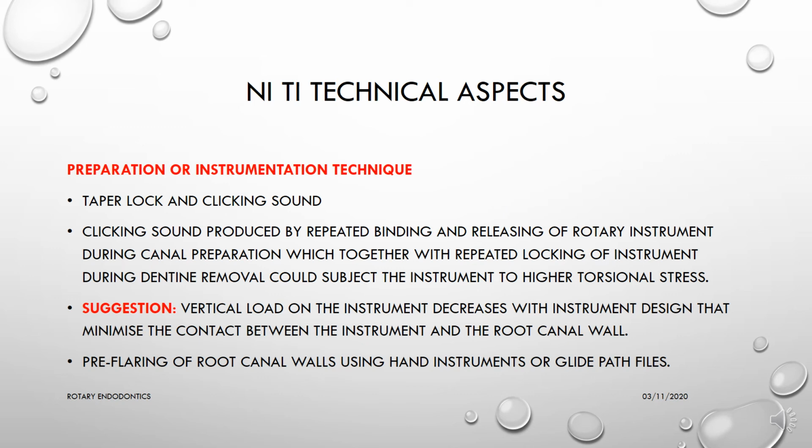Avoid taper lock and clicking sound when using rotary files for root canal preparation. The clicking sound is produced by repeated binding and releasing of rotary instruments during canal preparation, which together with repeated locking of the instrument during dentin removal could subject the instrument to higher torsional stresses, leading to instrument fracture. The vertical load on the instrument decreases with instrument design that minimizes the contact between the instrument and the root canal wall. Pre-flaring of the root canal walls using hand instruments or glide path files will reduce this vertical load and prevent the taper lock as well as the clicking sound.